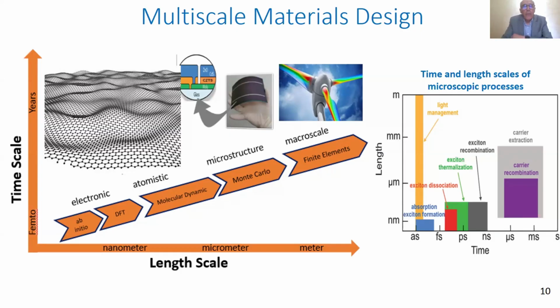The length scale is very important, but time scale is also important to be able to study microscopic processes. For example, the time scale for absorption of light and exciton formation is less than femtosecond, from the attosecond to femtosecond. And the exciton dissociation is less than picosecond, while exciton thermalization is of the picosecond, and so on. And for example, for carrier extraction and carrier recombination, the time scale is between microsecond and millisecond. So it's important to know which approach to be used for which design and for which characteristic and properties.